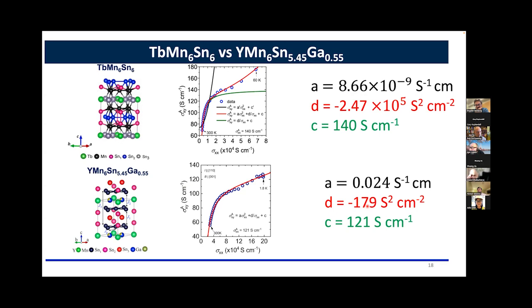And going back to Anand's question, yes, the scattering of phonons was considered in a seminal paper by Patrick Bruno, and they showed that phonons do not contribute to the extrinsic Hall effect. However, that argument was actually based strongly on the fact that phonons are just charge fluctuations. I even verified it with Patrick personally, and he said that yes, the argument would not apply to spin fluctuations. So spin fluctuations have not been considered. We need a theory similar to the Crépieux and Bruno theory for phonons. We need to do something similar for spin fluctuations, which we haven't done yet.